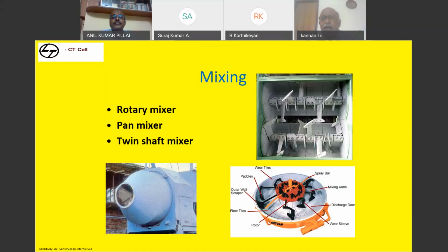Always during maintenance, please check all these wear plates and your blade position. If the blade is worn out, you have to check it and change it. Always adjust the springs so that the arms are in perfect position. If the inclination changes even a little, your mix will not be perfect. The mixing efficiency totally goes out.